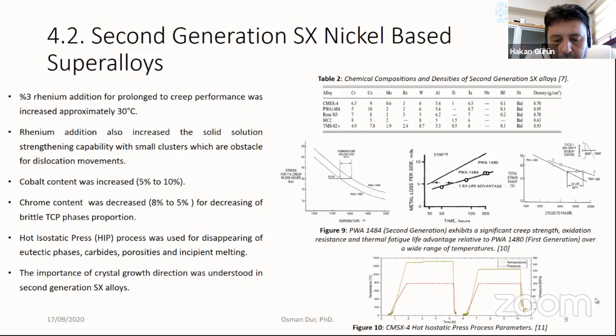In the second generation, alloy designers added rhenium for increasing creep performance. This addition gives approximately 30 degrees Celsius advantage. Rhenium also increased the solid solution strengthening capability with small clusters, which are obstacles for dislocations. Cobalt content was increased from 5% to 10%. Chromium content was decreased from 8% to 5%, to decrease the proportion of TCP phases.